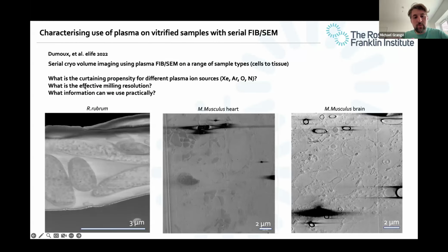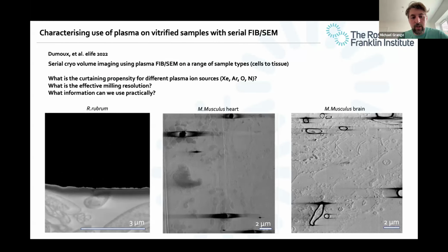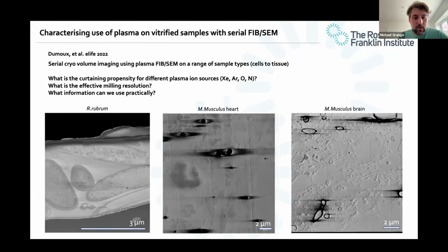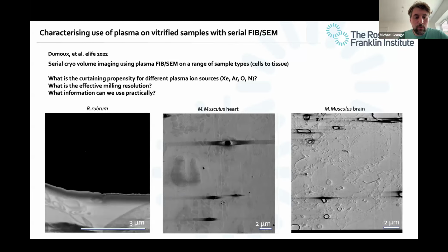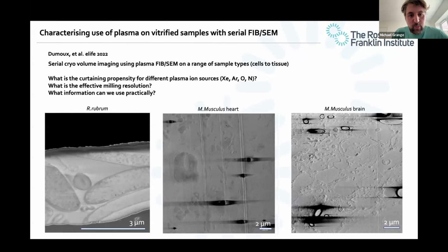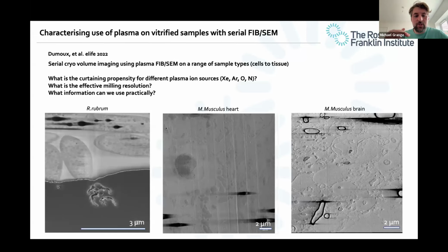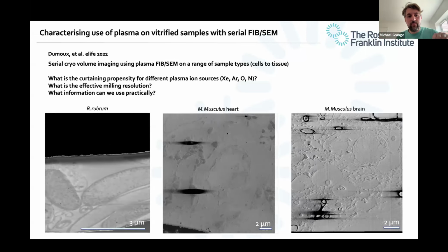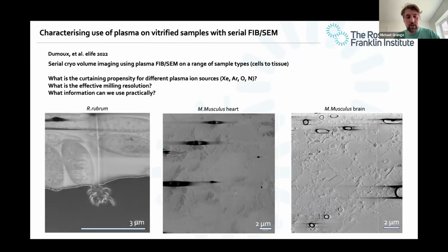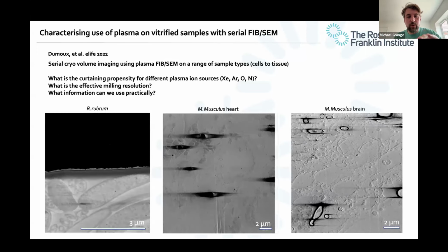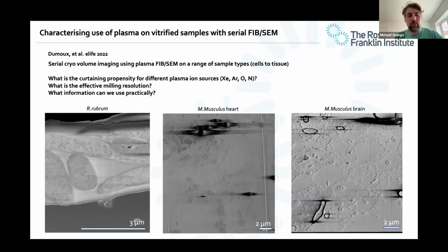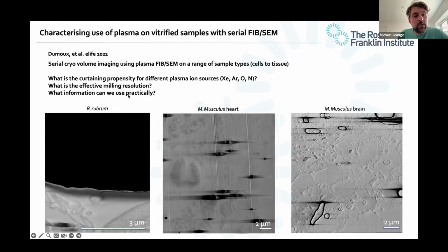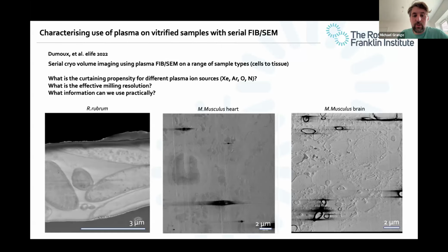Obviously, different parts of samples mill at different rates if they've got a different content. And what we want to understand is whether the different plasma ion sources had different propensities for this charge to build up. Curtaining, because what this curtaining is essentially is a topological profile. How flat that sample is will be determined by how many differences in the curtaining profile we get. We want to understand what the resolution is and what information we can use practically.